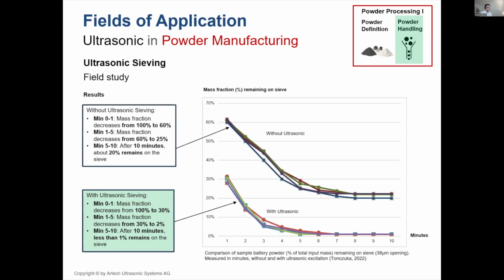As you can see from this graph, the x-axis shows you the minutes, and the y-axis the mass fraction in percent of the powder remaining on the sieve. Okay, so from 0 to 1 minute without ultrasonic, 60% of the powder was still remaining on the sieve, whereas with ultrasonic, only 30% was remaining on the sieve after 1 minute.